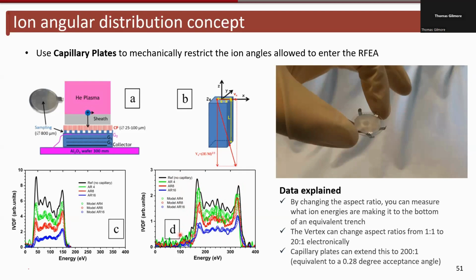But you can see here different ion energy distribution functions at different depths. And you can see, for example, as you get narrower and narrower acceptance angles, fewer and fewer ions made it to the bottom of the trench. Remember, the area under this curve is the ion flux. So in this case, the ion flux is decreased by more than a factor of 2, and in this experiment, it's decreased by nearly a factor of 4. If you think about it, this is actually a measurement of the etch rate as a function of depth. You can also see that low energy ions are lost faster than high energy ions in these cases.